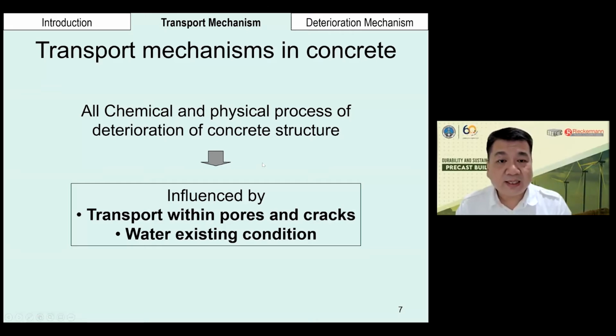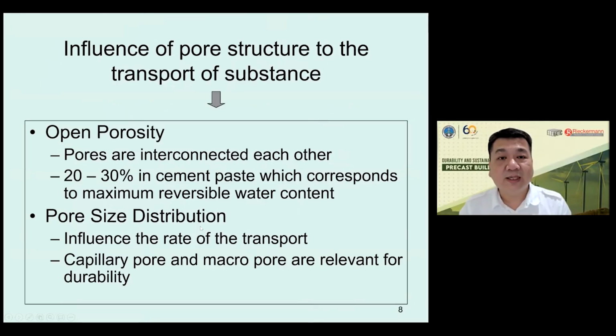Now, for the transport mechanism of concrete, when I say concrete, you can imagine a hard sponge with many pores. The deterioration is normally influenced by the transport within the pores and cracks and the water in the concrete. Just for the information, the porosity in the concrete normally is higher for a high water to cement ratio. And normally the pores are interconnected. And 20 to 30% of the cement paste is pores in the concrete.